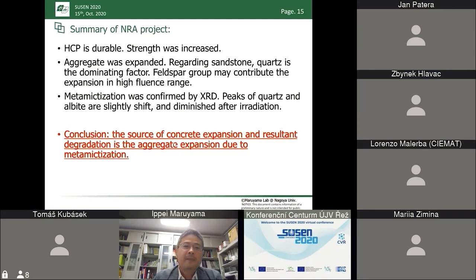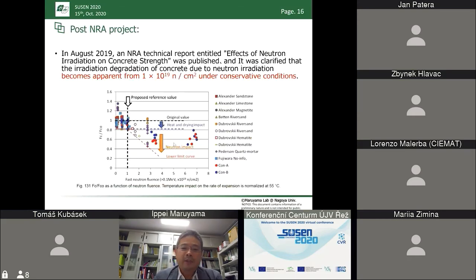So after doing this project, the NRA published the technical report, which mentioned that 10 to the 19th neutrons per square centimeter is the threshold for showing the reduction of the physical properties of the concrete. Therefore, the utility has to show the concrete soundness above 10 to the 19th neutrons per square centimeter of neutron fluence. Therefore, the new Japanese project was launched by the Japanese METI.